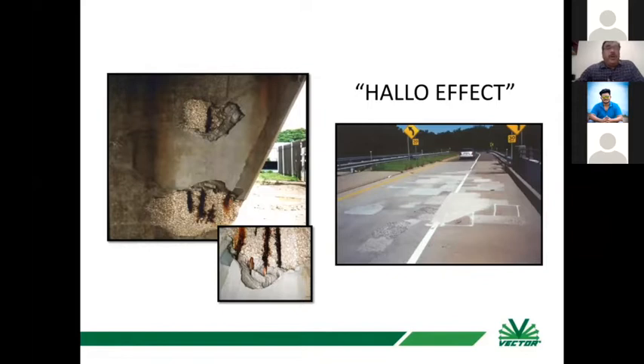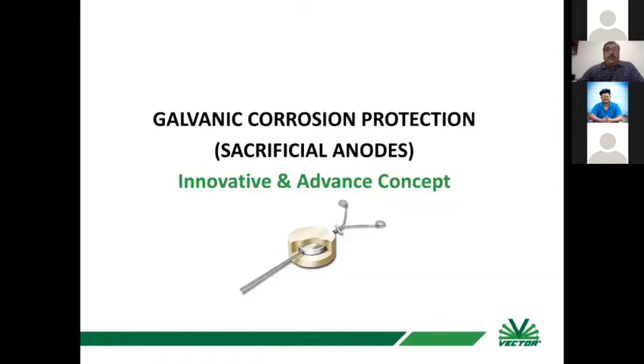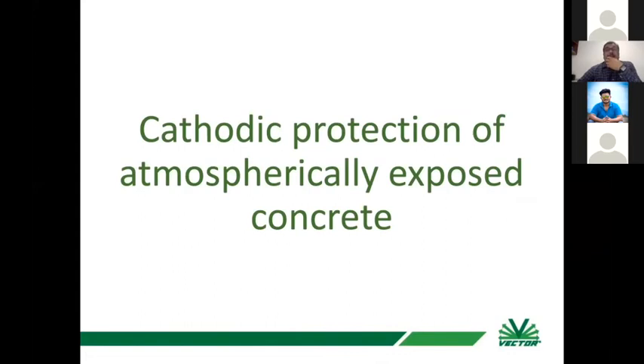If you want a long-term repair, we need to incorporate some system. We can use a galvanic corrosion protection system, which is an innovative and advanced concept, and it is very good for atmospherically exposed concrete. In case of submerged concrete, we don't have much free oxygen available in the water. So there the corrosion rate, particularly in the deeper sea, is less.